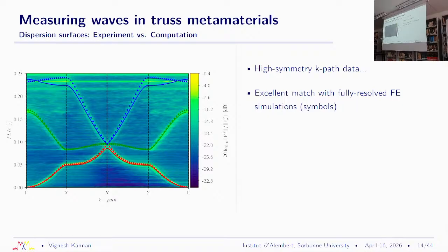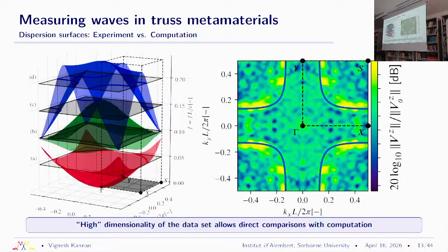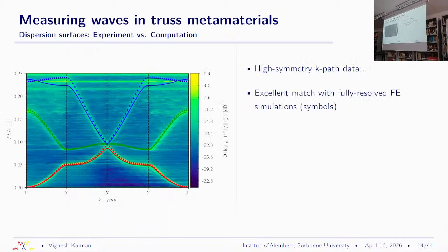And so now if I show you the k-path data, which is exactly the same data as before, but just unwrapped along this line. The color map is the experimental data. The lines are from beam-based finite elements. So, if I'm not wrong, Bastian was using Timoshenko beams. And the solid points are from fully resolved calculations. So you resolve the beam as a bunch of 3-dimensional elements, and so these are fully resolved finite element calculations. And it turns out for the first 2 modes, the beam-based finite elements was doing a great job, and at some point it started becoming less accurate when you go into higher modes.